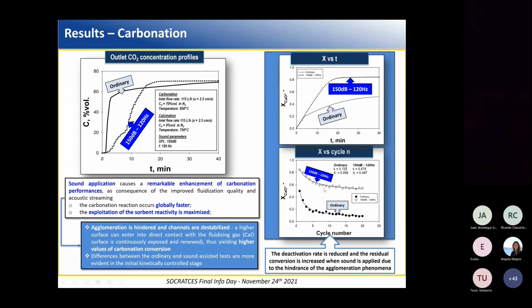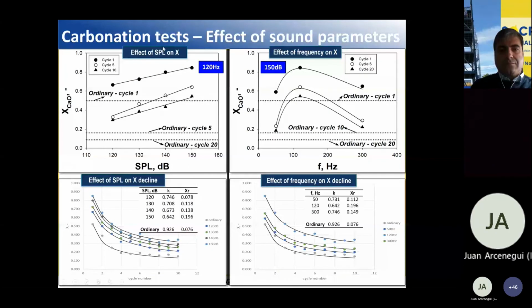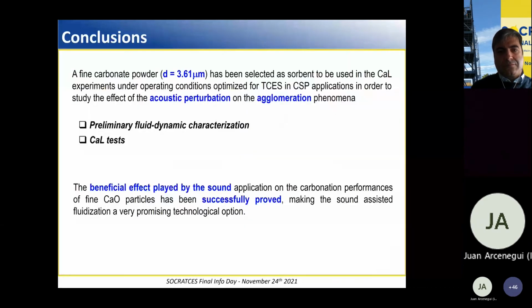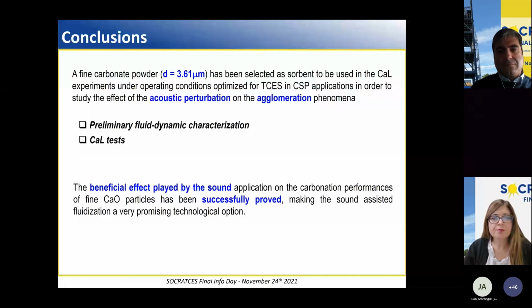And so, to conclude, in this study, we investigated the possibility to exploit the high reactivity and multicyclic stability of fine limestone particles in the sound-assisted fluidized bed reactor for thermochemical energy storage in concentrated solar power applications. In particular, we've successfully proved the beneficial effect played by sound application on the carbonation performance of fine limestone particles, making the sound-assisted fluidization a very promising technological option. That's all. Thank you for your kind attention.